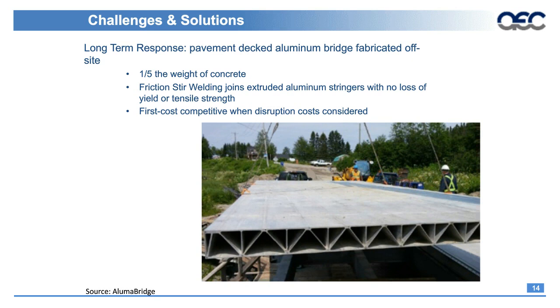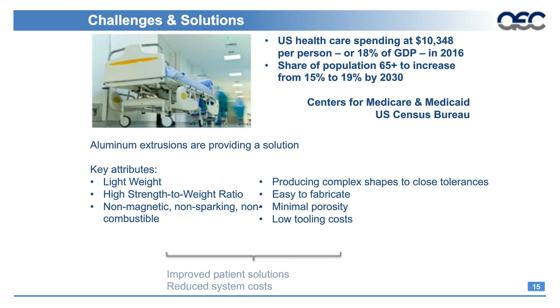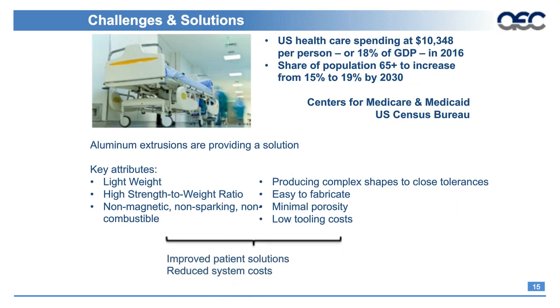But in the particular bridge example, you actually have several very large extruded multi-hollow sections that are friction stir welded together off-site. So basically, these bridges or these bridge decks can be pre-built in a modular fashion and then moved to the bridge site. So we start to decrease the amount of time that that bridge is actually out of service, which is a very key part when we think about our daily lives and when construction is going on and the interruptions that you face. So in this particular instance with the aluminum bridge deck, you're looking at a rapid deployment of a bridge.